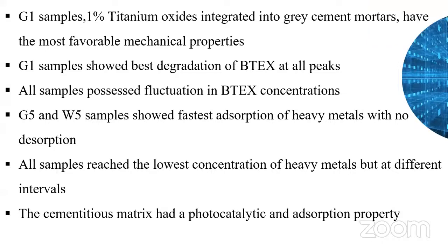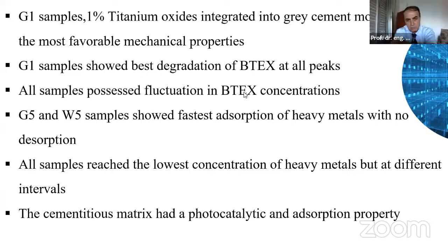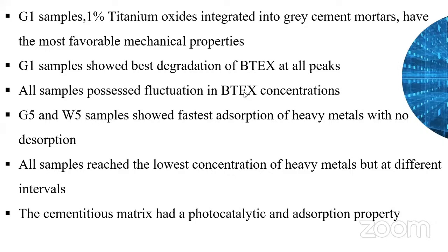Finally, we can conclude that mortar containing gray cement with 1% of titanium had the best mechanical properties, showed great results with the BTX degradation, and mixes containing 5% titanium showed best results with the removal of heavy metals.